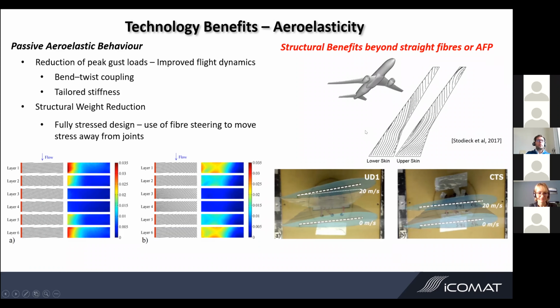Another thing that happens when you steer the fibers and tailor the load paths is that you can more uniformly stress the wing. You can move stress concentrations away from joints, for example, and spread them across the laminate, so you're using more of the composite. And this is an area which we are currently looking into together with the Ministry of Defence, where we have a contract.